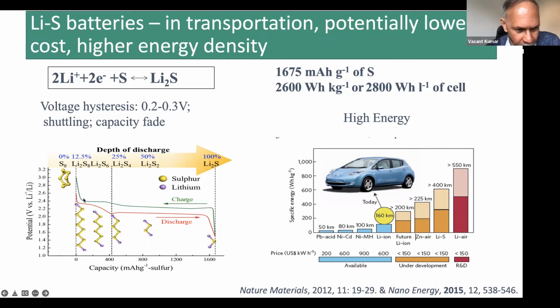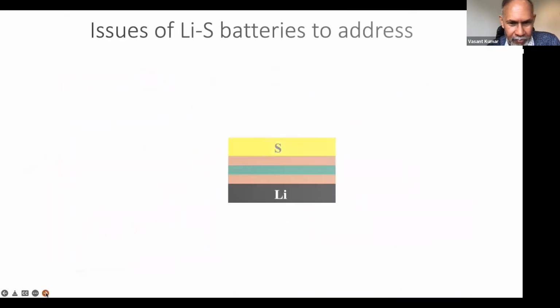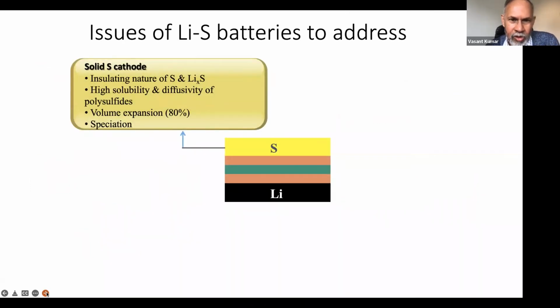However, if all that energy could be used, it has a very, very high capacity. This is a picture of the possible applications in the future, and the price, I think, is still valid even after 10 years. So what are the problems with lithium-sulfur batteries? The solid sulfur cathode, the insulating nature of sulfur and lithium sulfide, the very high solubility and diffusivity of intermediate polysulfides. The volume expansion and contraction between cycling is very large, and the speciation is another issue.